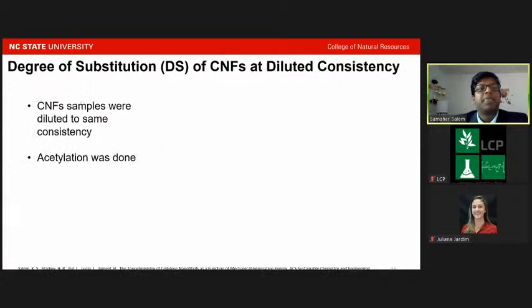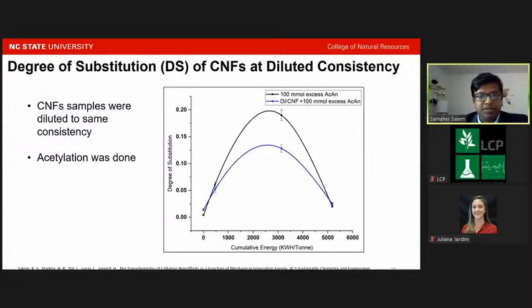So what we did, we took the nanocellulose samples again and diluted them to the same consistency. We ran the same reaction again, did the acetylation, measured the FTIR to confirm the substitution, and then also measured the degree of substitution again. And we could see that a similar trend was followed like before. With the increase of the energy, they reached a maximum value. And after reaching the maximum value, with the increase of energy and fibrillation, the degree of substitution decreased. However, the overall value of the degree of substitution was lower for the diluted samples compared to the original one.